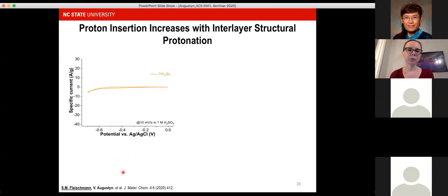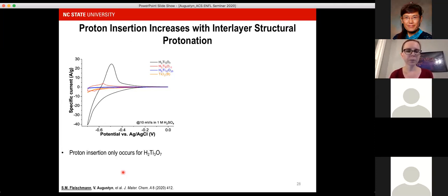Now for the electrochemistry, when we started with the most high temperature phase, when we cycled that in an acidic electrolyte, we saw essentially no charge storage process taking place. We start to add more interlayer protons, go to a lower temperature, still nothing. Then we start to see the presence of something that looks like maybe some electron transfer taking place, but the specific current was fairly low. But in the case of the most protonated material, we saw the most significant specific currents. So the significant proton insertion seemed to only occur for the H2Ti3O7 phase, the most highly protonated phase.